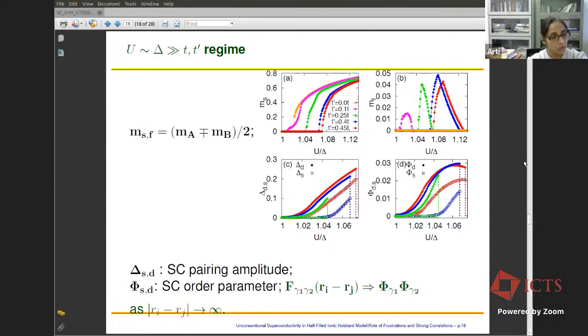Now let's look at the superconducting pairing amplitude. This is the study on the 2D square lattice, and we looked at both the D wave and the extended S wave pairing amplitudes. What we see is that one needs a finite strength of next nearest neighbor hopping to turn on any of the pairing amplitudes. For example, the D wave pairing amplitude turns on only when the second neighbor hopping is larger than 0.1 times the nearest neighbor hopping, and the extended S wave pairing amplitude turns on when the second neighbor hopping is at least 0.35 times the first neighbor hopping. And as the strength of the second neighbor hopping increases, the range of U by delta over which the pairing amplitude remains non-zero increases, and also the strength of the pairing amplitude increases.